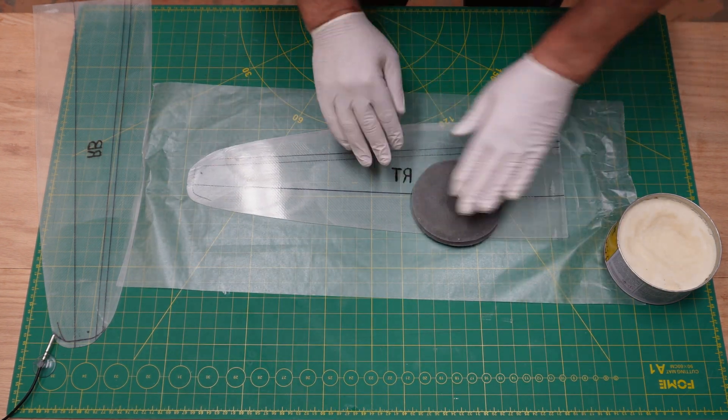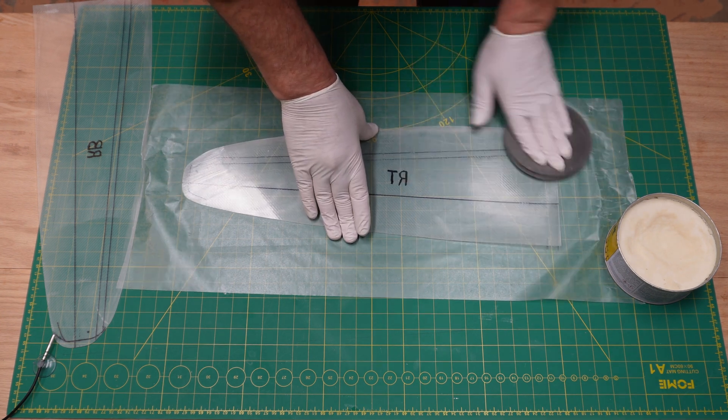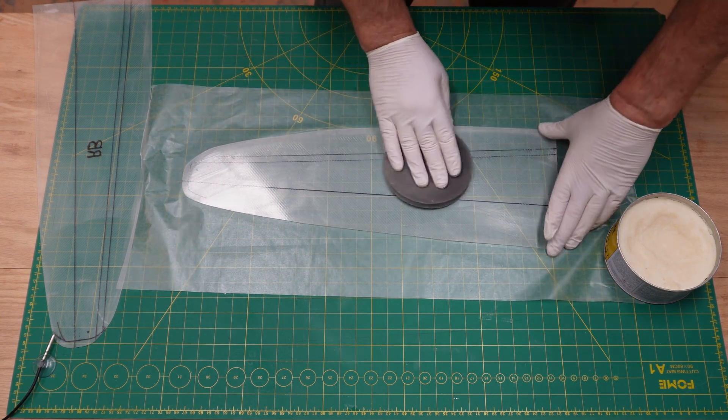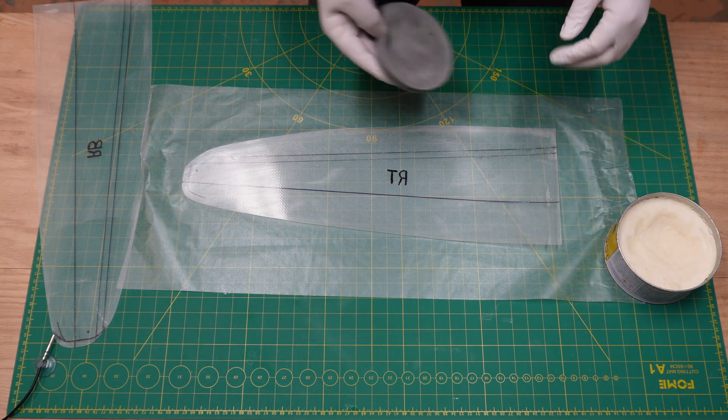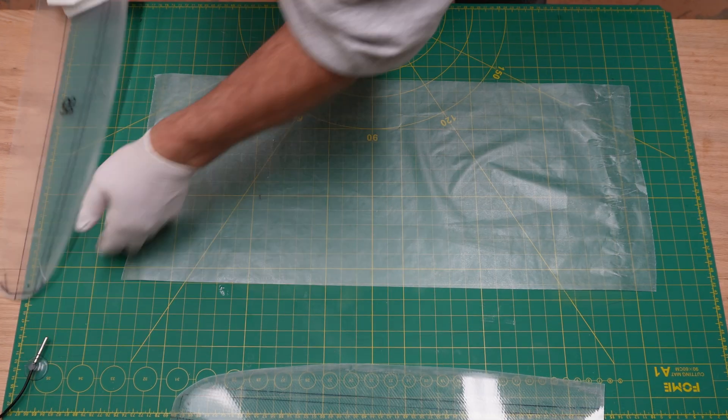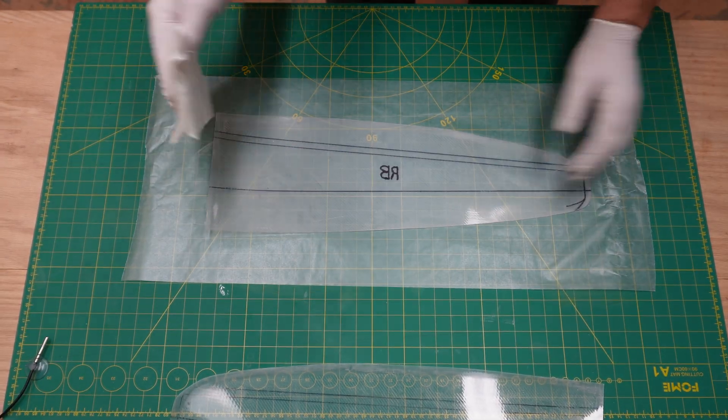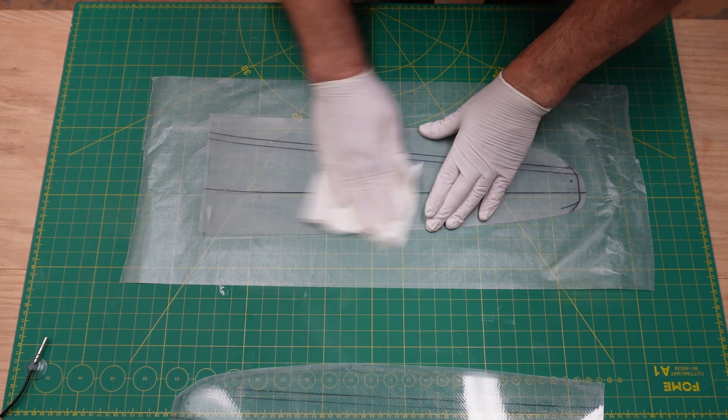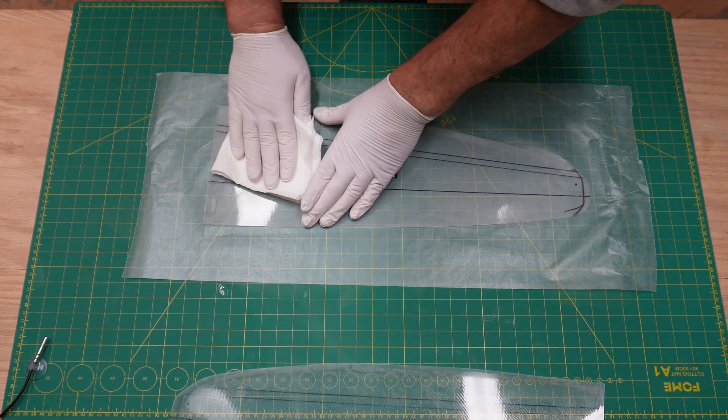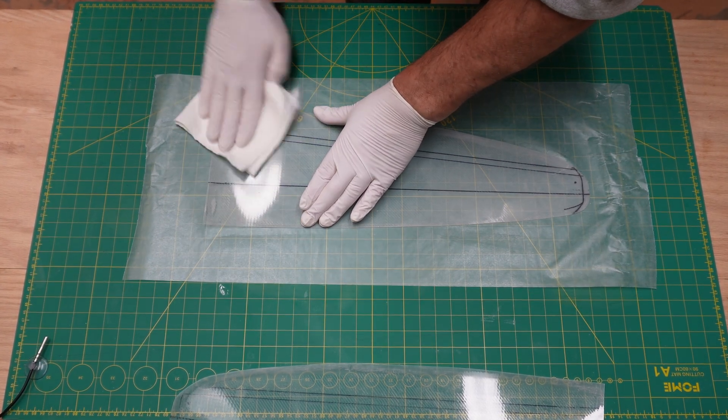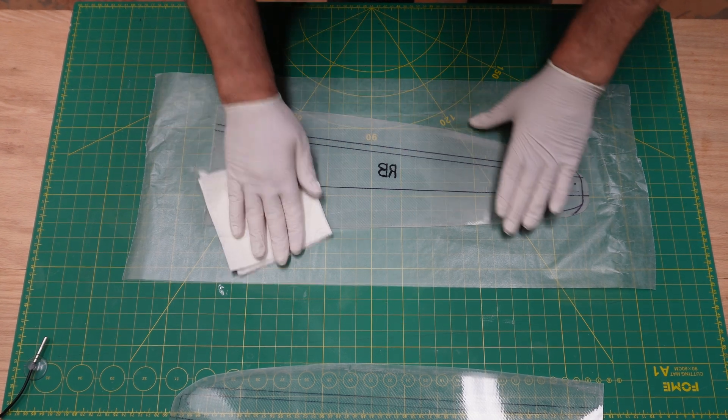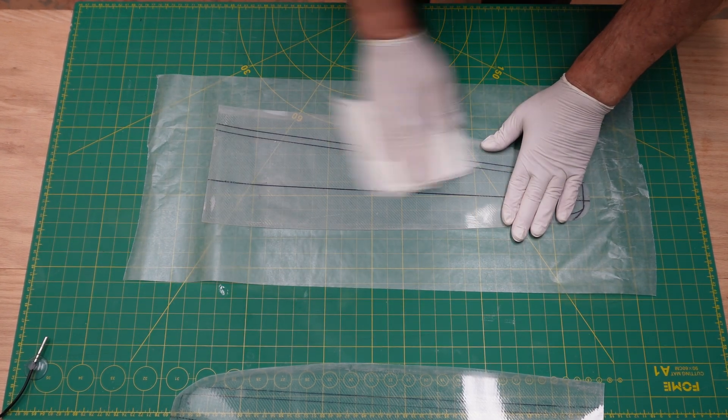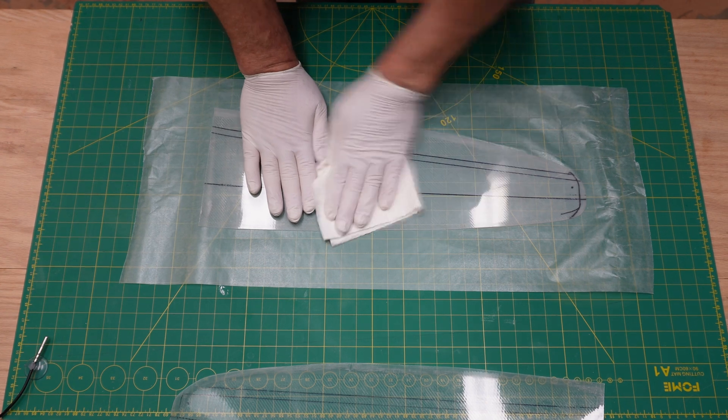You put it on, let it haze, then you buff it off with a paper towel. Then you let it sit for 10, 15, or 30 minutes. That creates a hard shell on the mylar that you want. You can coat this three, four, or five times. It's just gonna make that shell even thicker and better for you in the long run.